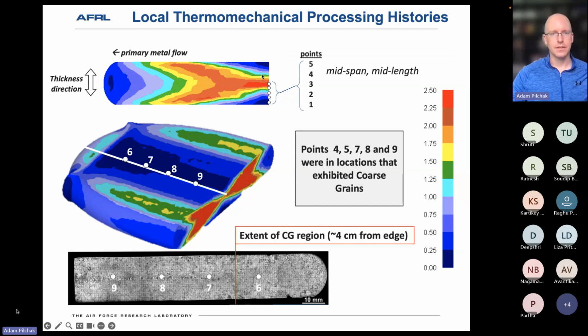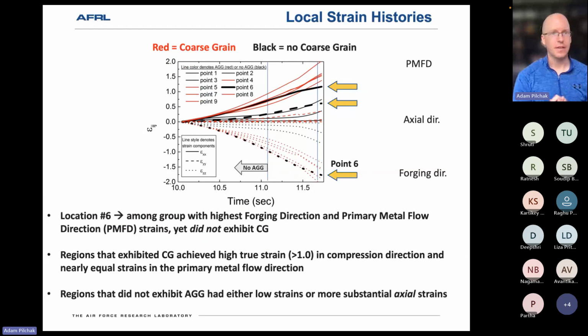So this is again the continuum FEM solution. We looked at a variety of points here, 1 through 5, with 5 being right in the center, where we saw the abnormal grains forming. You didn't see them so much in 1, 2, or 3. Similarly along the original bar axis, we went to these points that correspond with our characterization locations. Points 7, 8, and 9 all had abnormal grain growth present. Point 6 is the one you want to pay attention to, where we did not observe any abnormal grain growth.